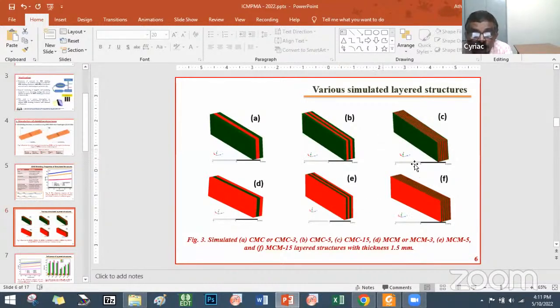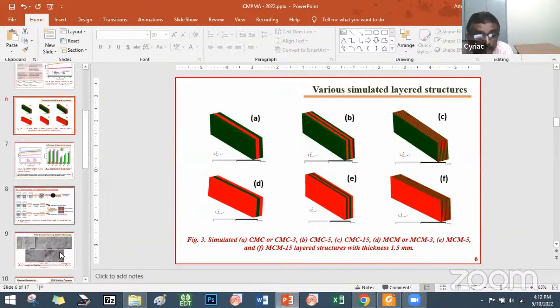The last one, the 15 layers, is quite hard to fabricate. We don't know about the fabrication of this particular one. We have fabricated up to here, and it was matching well. This one is a little bit hard because the layers are very, very thin. But if you increase the number of layers, there is definitely an increase in the total shielding effectiveness for the MCM composites,